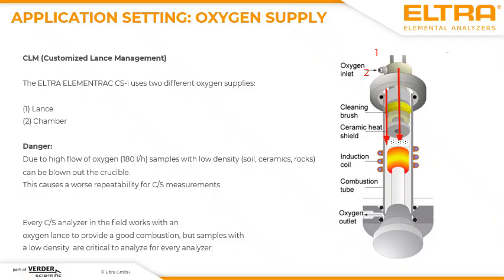On the other hand, you have the chamber oxygen supply. When you're only working with the lance oxygen supply, you can make sure on the one hand that the sample is very well combusted, but the more finely divided your powder is, the more trouble you could get with swirling of the sample. This means the finely divided powder is swirled out of the crucible because the high stream of oxygen is put on the crucible and the finely divided powder is blown away.